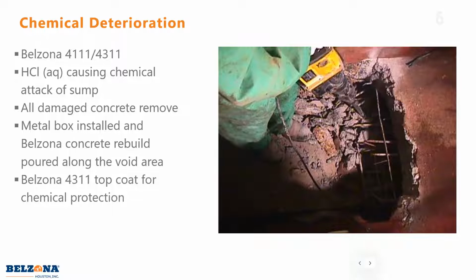So what happened was they installed a new sump box, and we used the Belzona concrete materials, 4111, to pour along the void areas of the box and the edges. And then 4311, which is actually a staple acid resistant coating we have that's mainly for concrete, but can be put on anything, was applied for the chemical protection.